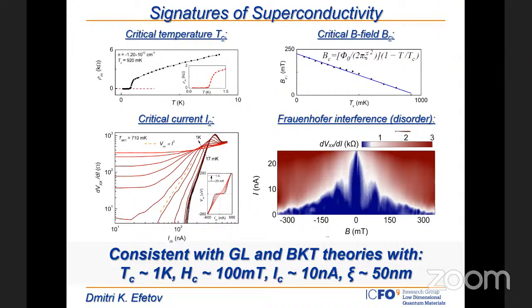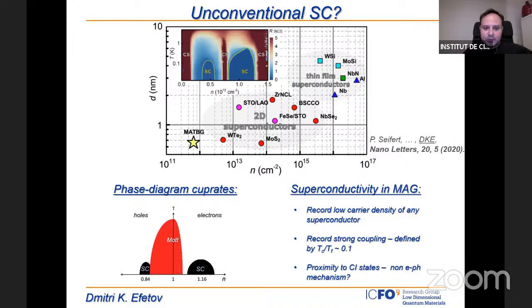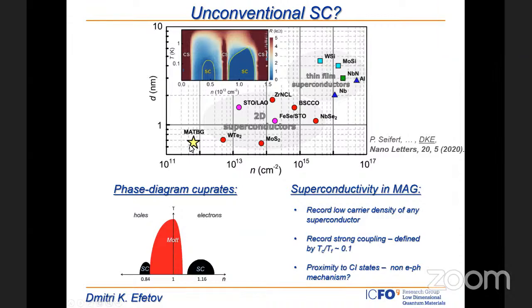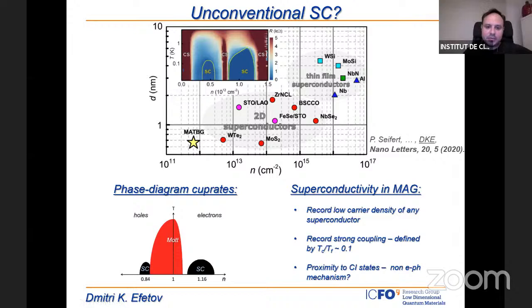Could I ask my question again, please? What is the D? D is thickness. Thickness of what? Thickness of the material, of how thin you can make the material. Aluminum, but these are bulk materials. So the aluminum, yeah, exactly. If you prepare it in 2D films, if you make thin films out of aluminum, I think you can make it maybe 5 nanometers thick or so. That was the point here. And the graphene thickness is 0.6 nanometers, so it's 10 times thinner than the thin film limit of aluminum.